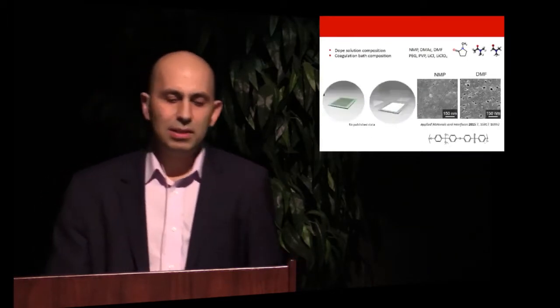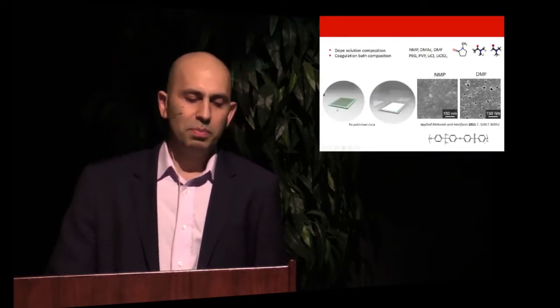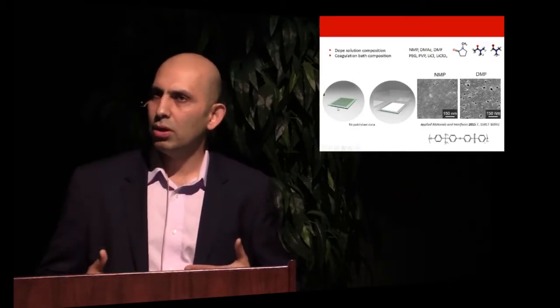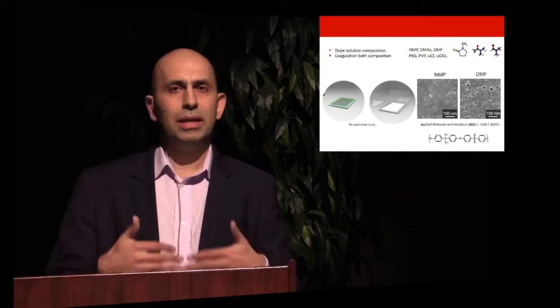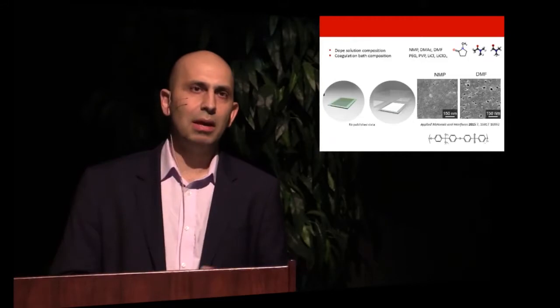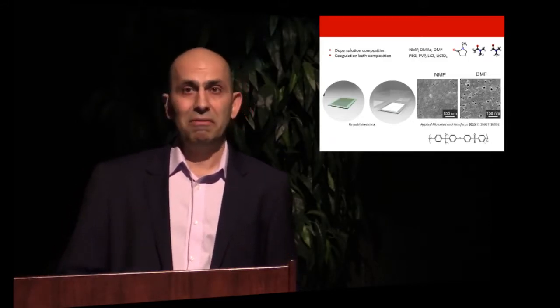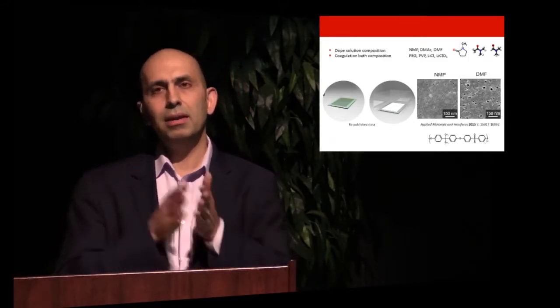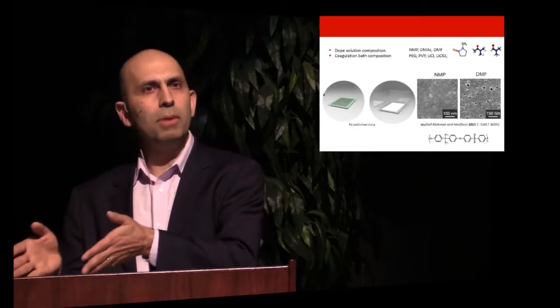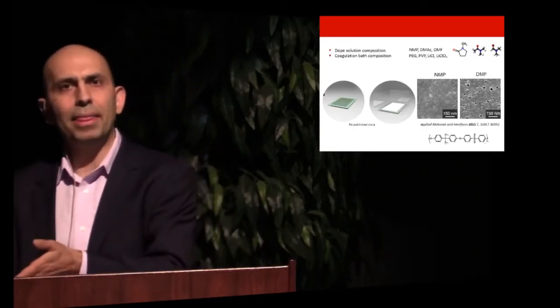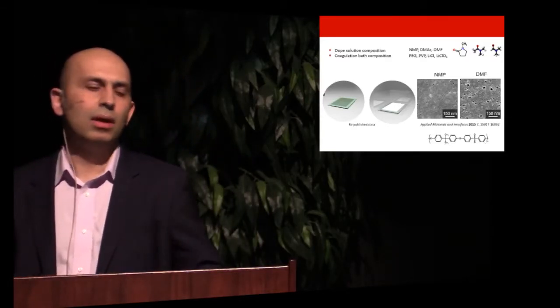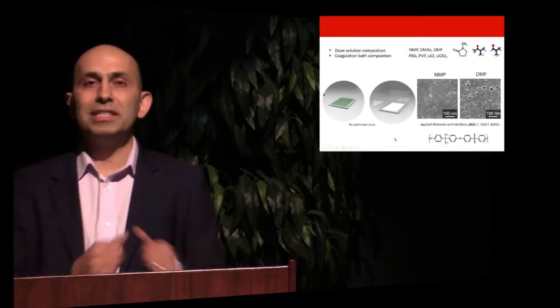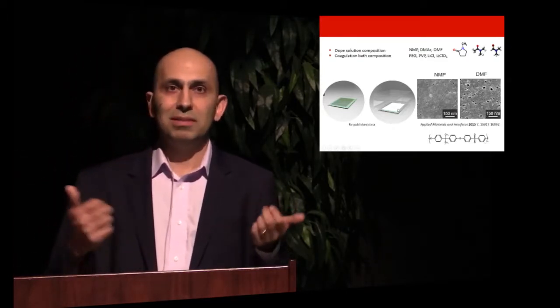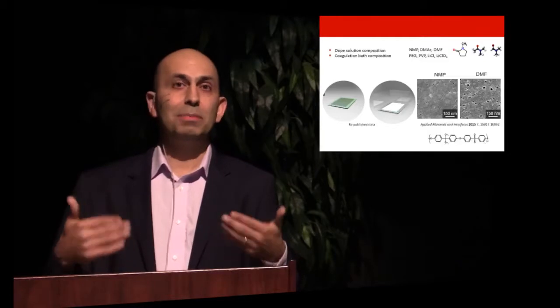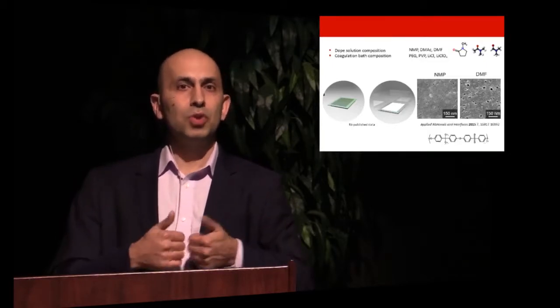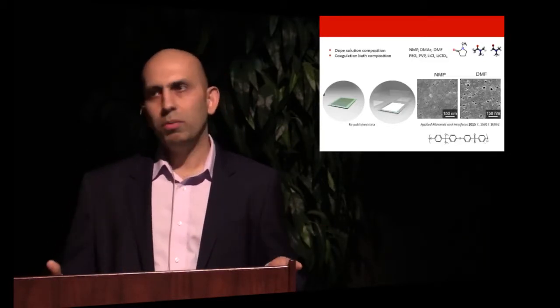And here's the process in industry too. They cast this polymer solution on a piece of substrate. It can be polyester, or a woven mesh like a nylon mesh, and then they put this whole composite into a non-solvent bath, which they call a coagulation bath. As a result, the solvent escapes because the new Gibbs energy situation is not favorable, so the solvent escapes and the pores remain in the matrix.